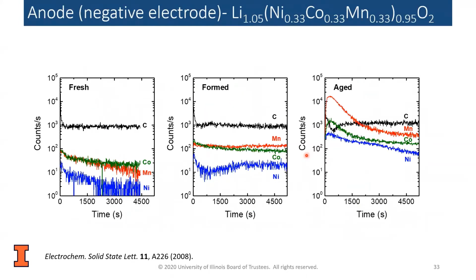So next are some examples of SIMS, of some fresh and formed samples. And basically, there's not a lot of difference between these two. Basically, much of the change you see is in some of the aged samples, the calendar life aging cycles. You'll see that this is actually an anode instead of the cathode that we described before. You see that there's a buildup of manganese at the anode side. And this indicates that there's manganese dissolution at the oxide surface, and it is being transported to the anode.